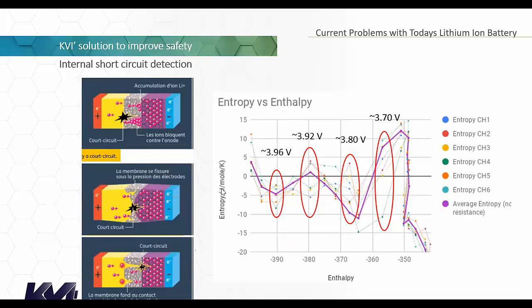Here we have found a solution, and I would like to very briefly cover it. So the solution consists of measuring the thermodynamics of the battery, entropy and enthalpy. It's very simple. If we can measure the open circuit voltage of a battery and how this open circuit voltage varies with the temperature of the cell, we can have entropy and enthalpy. And what we found actually in some batteries, there is a difference in the entropy data according to whether the battery has or doesn't have an internal short circuit. So this slide shows, for the solid line here in pink color, the entropy profile versus enthalpy of a cell that has no internal short circuit, this one, okay?